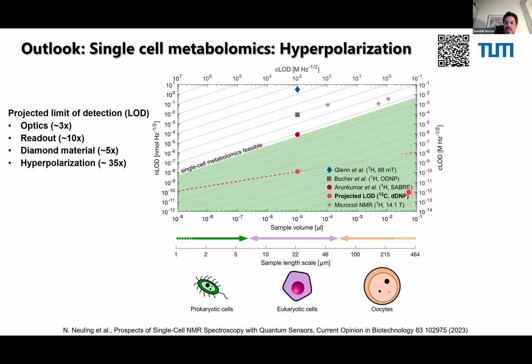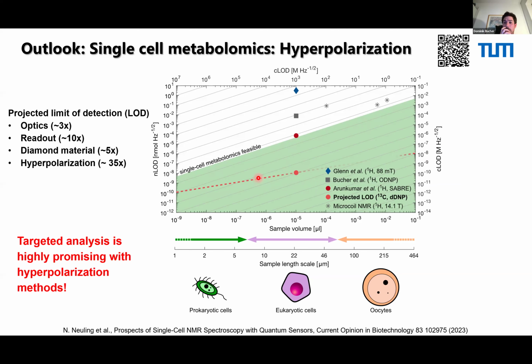And what we used here is a technique called dynamic nuclear polarization, where you basically cool down your sample to increase spin polarization. You add electrons and transfer this electronic spin polarization onto your nuclear spins. So, dynamic nuclear polarization. Then we end up here in a regime where we can detect metabolite concentrations which are interesting for biologists. So at the end, the answer will be here.